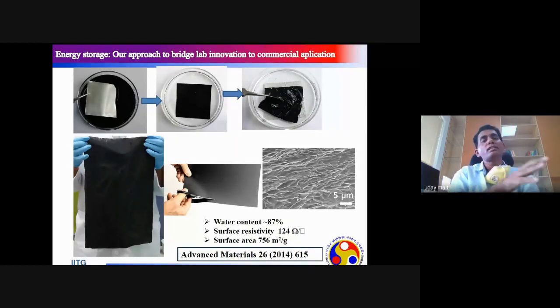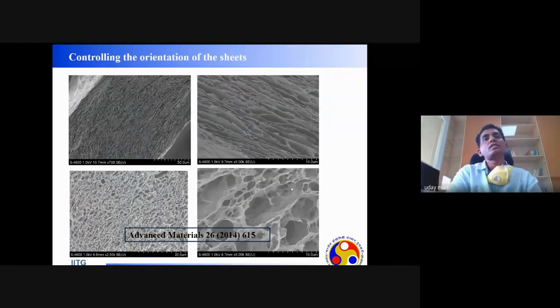We started with a metal plate, just dipped into the dispersion of graphene oxides. If you want to know the details, you can follow this reference which we have published here. You can see from this SEM image, where this is written as 5 micron, that between the individual graphene sheets there are many pores. That means there is no complete restacking of the graphene. By this strategy, we can reduce their restacking, and we can of course control the orientation of the sheets by tuning the gelation conditions.